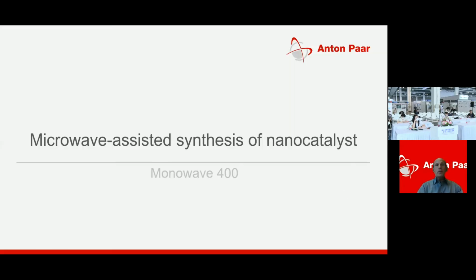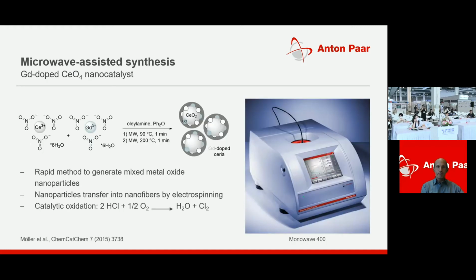Among the product range of Anton Paar, we find instruments for microwave-assisted digestion, as well as microwave-assisted synthesis. In this first example, we want to make use of the so-called Monowave 400 to prepare catalytically active nanoparticles for the oxidation of hydrogen chloride. The intended end product should be composed of cerium oxide with different concentrations of gadolinium as a dopant.